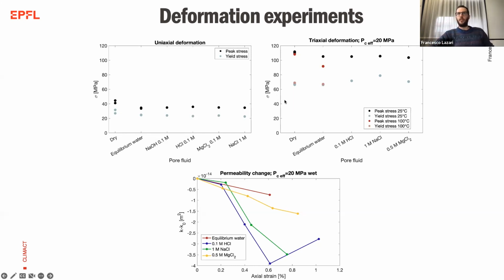On the second panel, instead, we have the experiments under pressure. In black and blue, we have the experiments at room temperature. In red, we have some experiments done at 100 degrees Celsius. Of course, the experiments at higher temperature are more representative of what's really happening to the rocks. So if you look at the room temperature ones, we barely have any weakening due to the presence of water, and we don't see any difference in the different fluid chemistries.